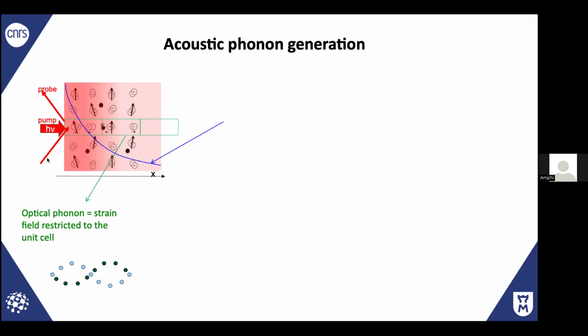And regarding the situation of acoustic phonons, as I told you, for optical phonons you have to induce a force in a unit cell. And for acoustic phonons, you have to induce a gradient. Acoustic motion is just what? It's a symmetric displacement of neighboring atoms. So in that situation you need to induce a gradient of pressure, a gradient of stress. This is what the blue line is, I forgot to tell you. It's typically the light absorption. Usually in a material, if you have above band gap excitation, light penetrates over a finite distance. So this is typically the profile of the light absorption.